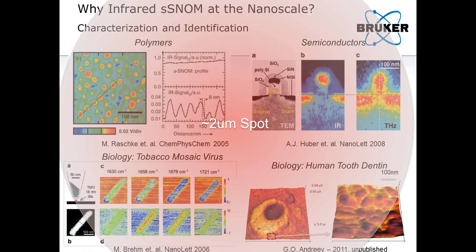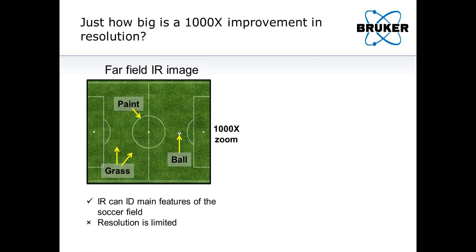So I mentioned repeatedly that these images are achieving resolution as low as 10 nanometers, and that would be over 1,000 times smaller if you were considering a 10-micron spot, if you were considering wavelengths as large as 10 microns, which is what you might use in an infrared microscope. So just to give you some idea of what a 1,000 times improvement of resolution looks like, I'd like to illustrate that on the next slide.